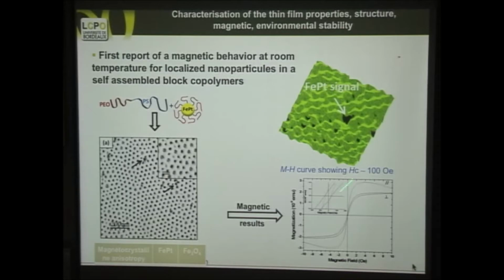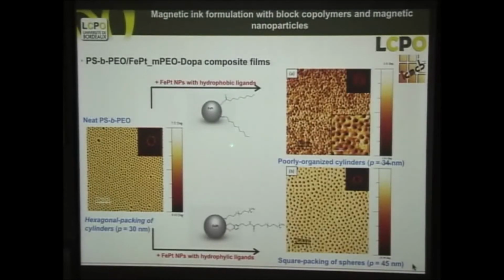The other thing that we discover here is that we have places, and that has to do with the defects that I showed you in the previous work, where these hexagonal patterns are not well organized and we have defects. Sometimes the particles go inside these defects for entropic reasons, because there is a lot of relaxation of these hairs that we have here, so they relax instead of being stretched.